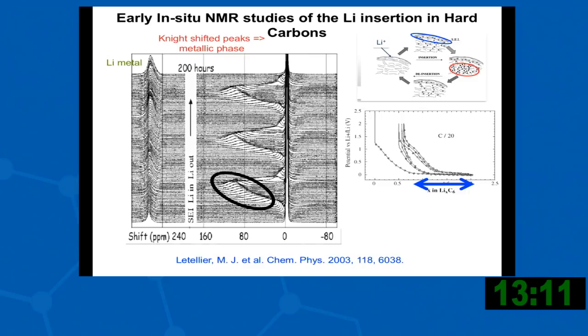Lithium NMR was done on hard carbons many years ago, and this was the pioneering work in in-situ NMR that we were very much inspired by. And what you see is the lithium NMR spectrum here. This is the lithium metal. And then when you discharge, you see very little changes in the sloping region, and then you see this large shift out to about 100 ppm. That shift is due to the Knight shift, which tells you that the lithium is seeing a metallic environment.